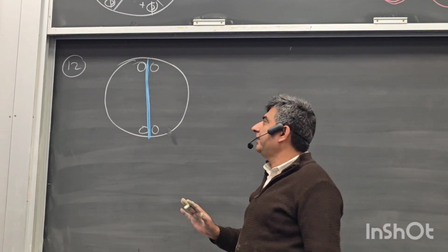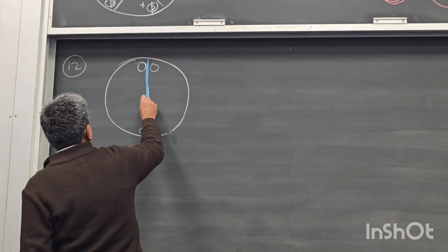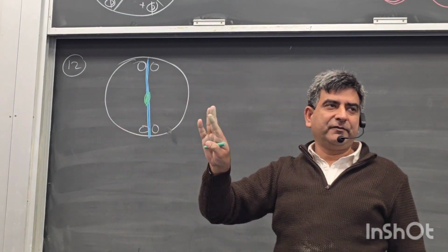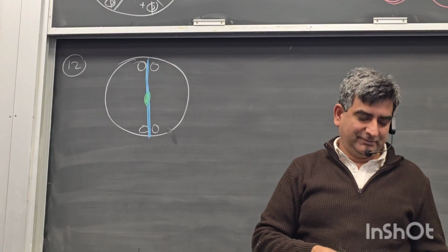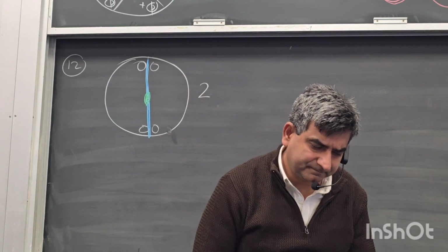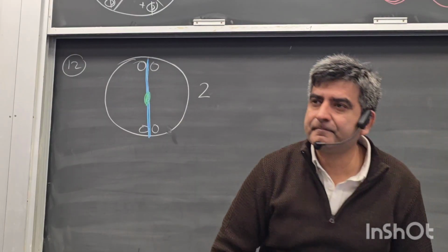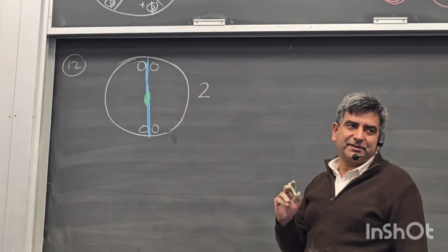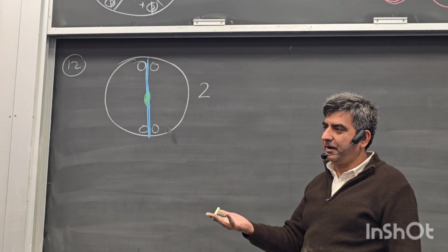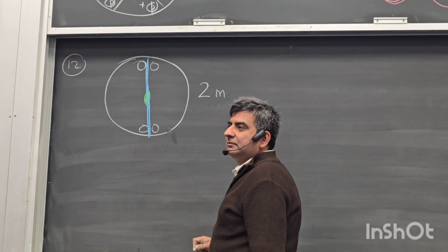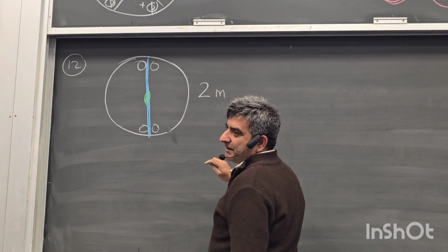Now this new mirror plane is, the axis of rotation is also vertical, it's coming out, the two-fold axis of rotation, and the mirror plane is parallel to it. In fact, the axis of rotation lies in the mirror plane. Correct? So the symbol for this is 2. Okay, so what should be the symbol for this? Just give a guess. This is a mirror plane M. But instead of writing forward slash M, we just write 2M. But the symbol for this really is not 2M, it's 2MM.